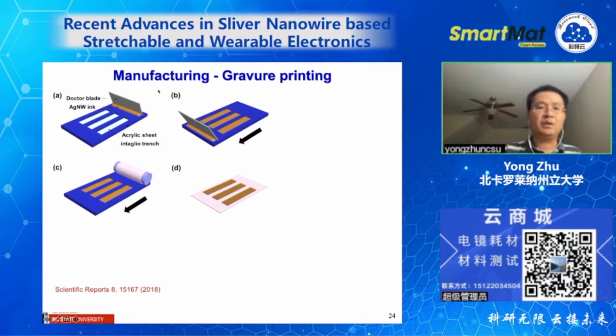Okay, gravure printing, simply put, you see here we have an intaglio trench. Then you put the inks in. You first use the doctor blade to put the inks into the trench, and then here is the substrate you want, the flexible substrate you want to print on. Then you essentially press the inks onto the flexible substrate. You roll the substrate and then print on.